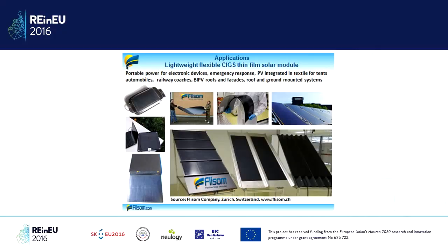So in any case, when I say thin film photovoltaics, basically what I'm talking about is different from silicon wafers. These silicon wafers are about 300 micron thick, and thin film photovoltaics are thin coatings which are applied on any surface. It can be glass, or it can be plastic or metal foil. And these are about 4 to 5 layers of roughly half a micron or 1 micron. So in total, we are talking about a 3 to 5 micron thickness coating applied on some surface.